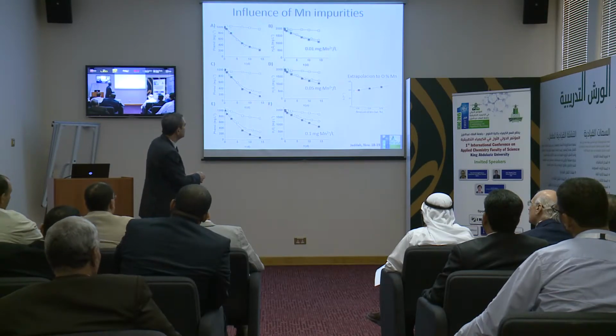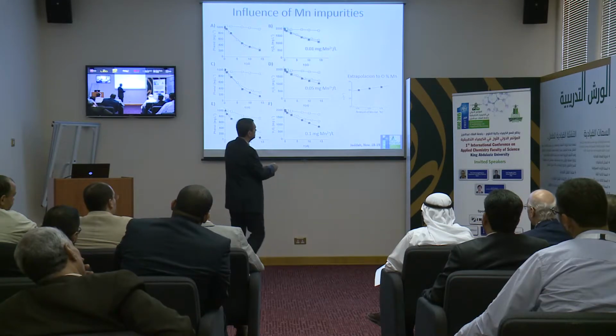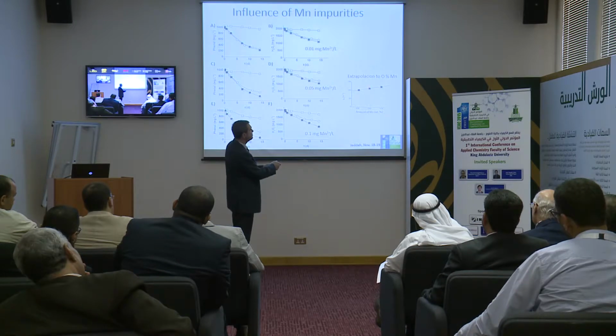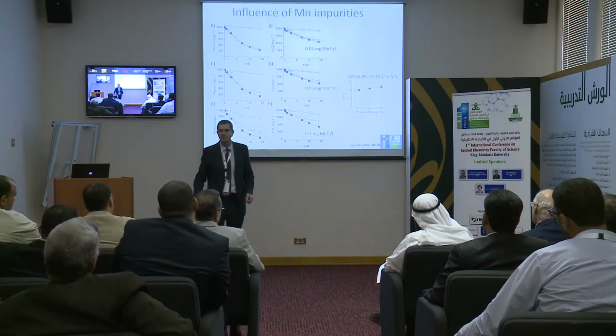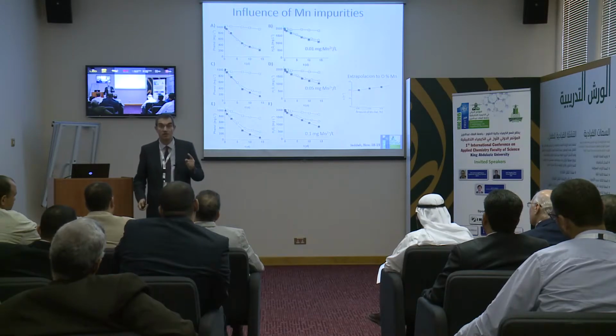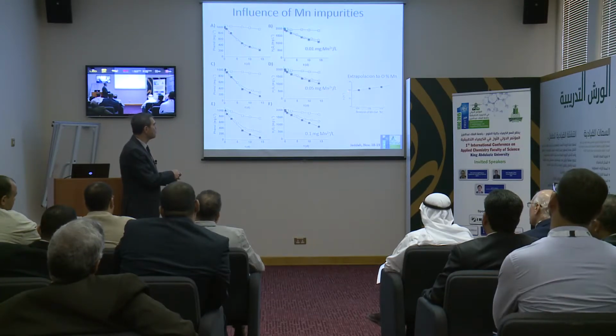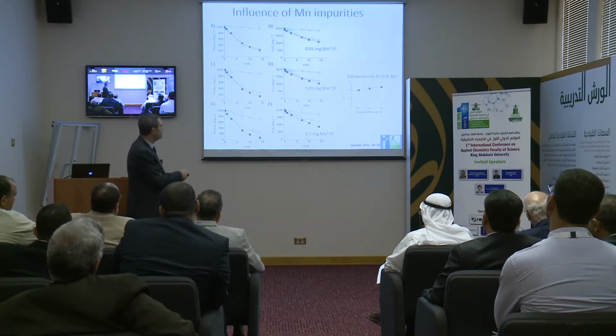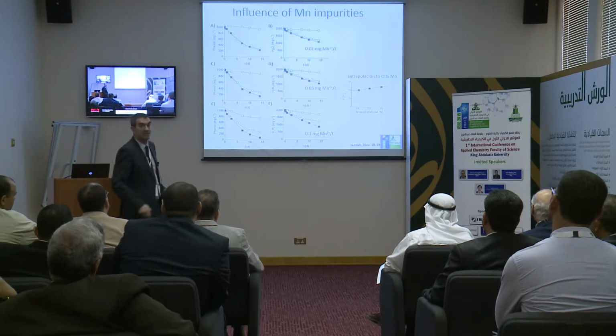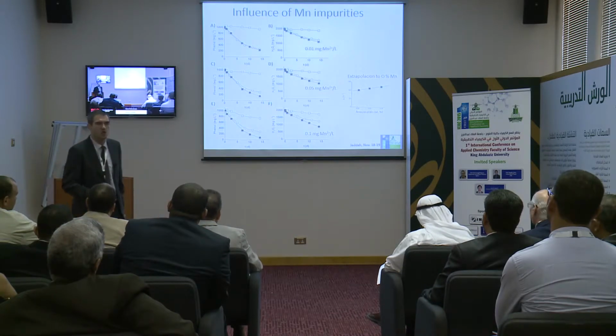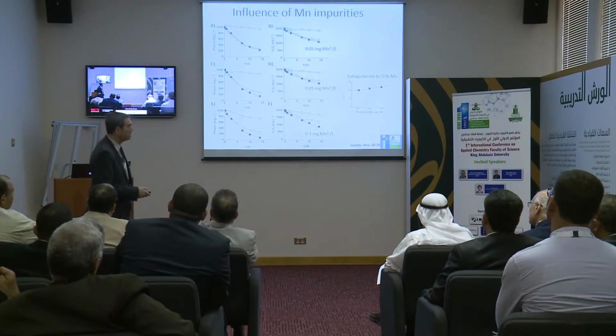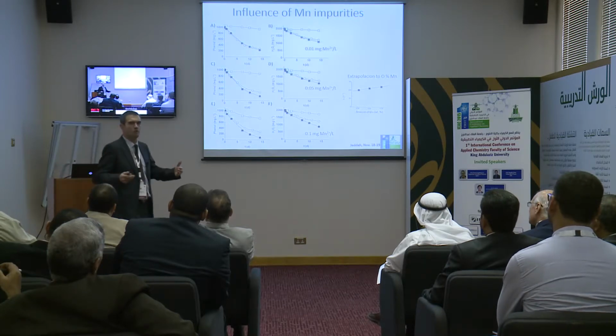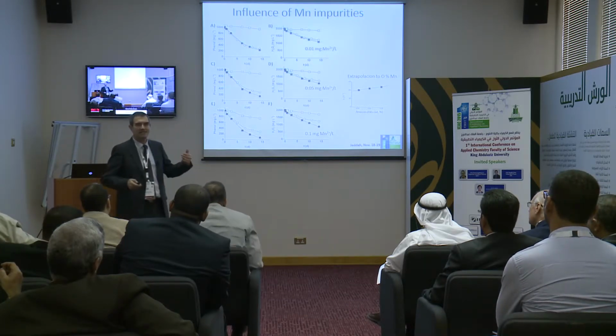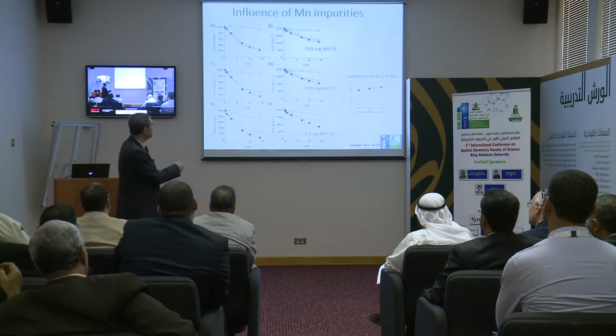So this is the plot that summarizes the influence of the reaction rate constant with the amount of manganese, and what you observe is that yes, there is some influence, there is some increase. But if you extrapolate to zero amount of manganese, something that probably is never possible to be done, but if you extrapolate this line, what you observe is that there is still a very significant activity of graphene without any metal. So basically, we cannot have a sample totally free of impurities, but we can study the influence of the impurity by making these plots at different concentrations of manganese.